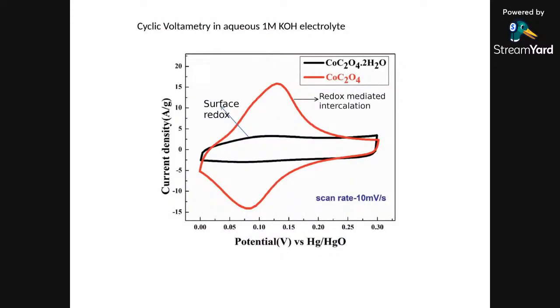Now you see this: when we have cobalt oxalate hydrate, it showed more surface redox behavior, dominated by surface intercalation. However, when we remove this water, we get much more intercalative behavior. Due to removal of the water, a much more porous structure has been created inside the rods, which led to diffusion of the hydroxide ion to a much larger extent. And that's why we get much higher energy storage, if you see the total area under the cyclic voltammetric curve at the same current rate. So this is the direct difference we got. And when you increase the intercalative nature, the surface storage remains there because it depends on the surface area. So overall you come up with dual performance.